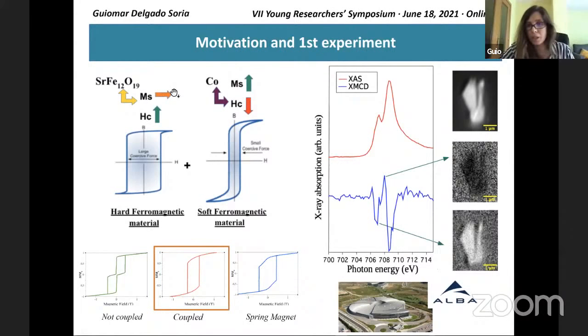First of all, we studied the magnetic coupling between a platelet of strontium ferrite with a cobalt overlayer. The ferrite platelet was characterized by X-ray techniques at the ALBA synchrotron, in the CIRCE beamline. In this image, we can see the XMCD spectrum that reveals the electronic transition at the iron L-edge. This graphic gives the characterization of the iron oxidation state and the crystallography of iron, and we can also determine the magnetic domains in the platelet. The change in contrast, black to white, corresponds to different photon energies and reveals that we have only one magnetic domain, which is out of plane.